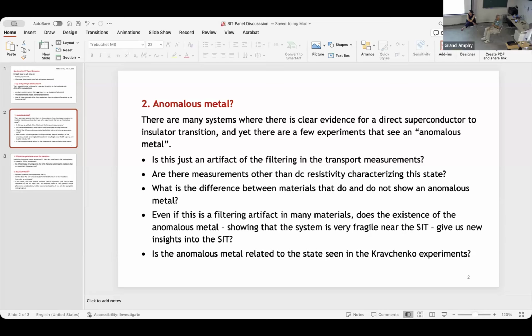But my impression is that what is important is the value of the sheet resistance. If you have a metal film of 50 kilo ohm per square, or say 50 ohm per square, then it will always be anomalous. You cannot convert this at accessible temperatures into an insulator. So you really need something that has several kilo ohms of sheet resistance, so that this physics can become active, right? That the localization with the help of interaction really takes place at some point.